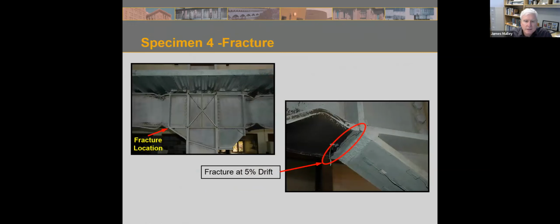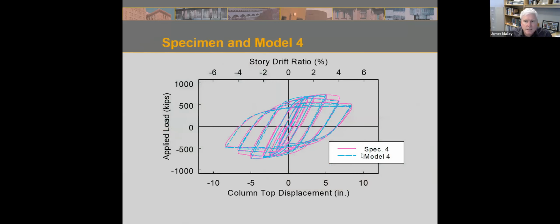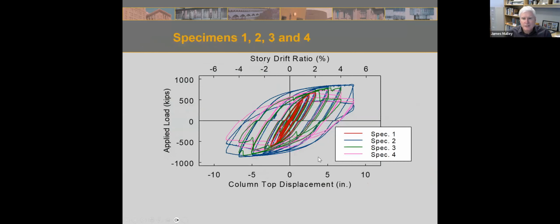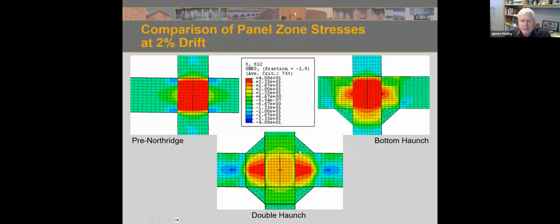And again, we felt pretty solid about that because we had multiple cycles at 1% drift, 2% drift, 3% drift, 4% drift, and 5%. Very large demands, probably more than we would ever actually see in one of the connections in a ground motion. Again, model with the finite element looked good. And then these are all the tests on top of each other, sort of showing the differences between the 4 tests. I didn't show you too much about the third test, but we'll show you that in a video here in a second. We did some finite element analysis to compare the test 1, 2, and 4.